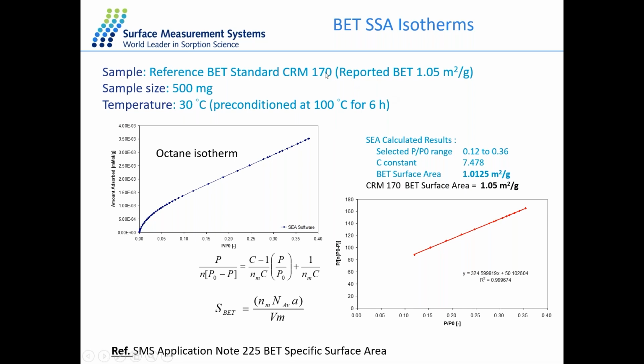In this case, the probe that we've used is octane. This is the resulting isotherm for our octane experiment. We've applied the BET surface area equation, similar to that of the nitrogen sorption equation, and we've obtained a linear plot for our BET line. What this is showing is that we've compared our technique's BET surface area to the literature technique with nitrogen sorption, and as you can see, our technique and the nitrogen sorption technique are in very good agreement with each other.